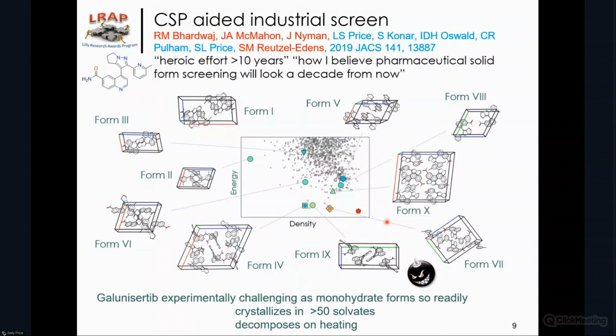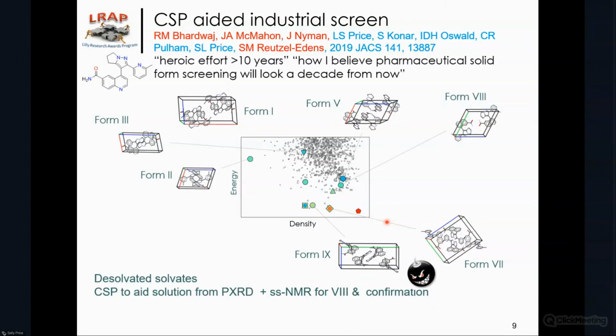Now, this system was hard to work on experimentally because it readily formed the monohydrate. In fact, it would crystallize with many, many solvents, so we got solvate structures rather than neat polymorphs, but also it decomposed on heating. So actually only 2 of the polymorphs could be grown by classical single crystal growth and diffraction, and the structure solved. The majority were desolvated solvates, and we were using the CSP generated structures to help solve these structures from the powder patterns. And when Form 8 had multiple solutions, we then went through calculating as well as measuring the solid state NMR of all of them to confirm these structures.